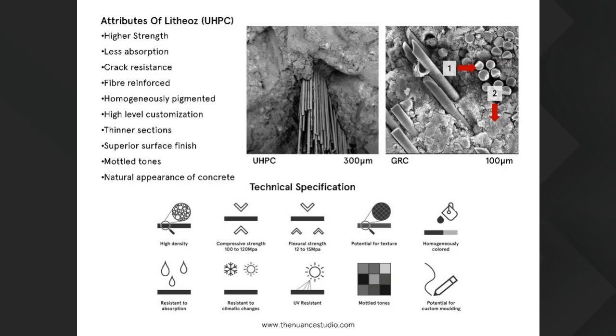On the other side, for a comparison, GRC, when it has been zoomed to about even 100 microns, you can see the kind of gaps and cracks that the material has. So this is one of the reasons that the UHPC has more strength and the absorption is much lesser. It is also resistant to cracks.